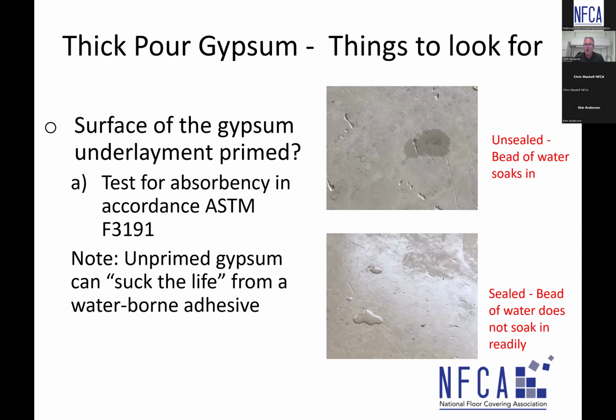Okay, so things to look for. We did what certainly was brought up, F3191. So when you get on site and you're looking for a thick pour gypsum, I told you that these manufacturers recommend it be sealed. Very common recommendation. When you look at the top picture, the water is just drinking right in, and it just soaks right in and it's gone. The bottom picture has a primer applied to the surface of the gypsum, and I'm not saying that water is not going to soak in, so don't misunderstand me there. And I'm not going to say that it's going to remain a bubble either. It could soak in and that water could dissipate.